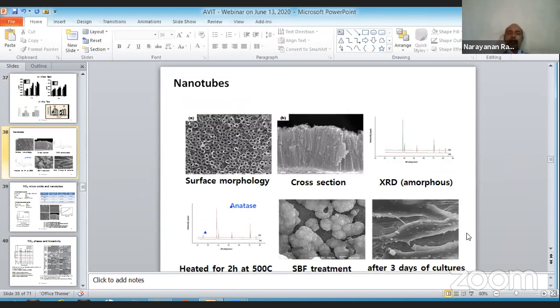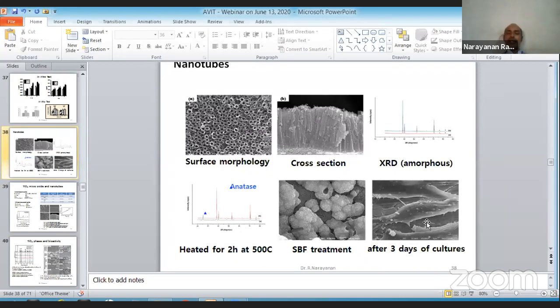So you can see the cells spread. So this is a surface, so maybe an oxide surface on titanium. So I treat it with osteoblast cells for certain days. Say after 3 days, you can see that the cells spread. This is the starting cell, and it has extended its arms. Okay, so this shows that my oxide coating on implants is very useful. So when it is placed inside the body, the cells will attach firmly and then spread. This cell is attached to another cell here. This cell is attached to another cell here. That means there's a cell connectivity, and therefore there will be better bone bonding compared to the surface without this oxide coating. So that's what it means.